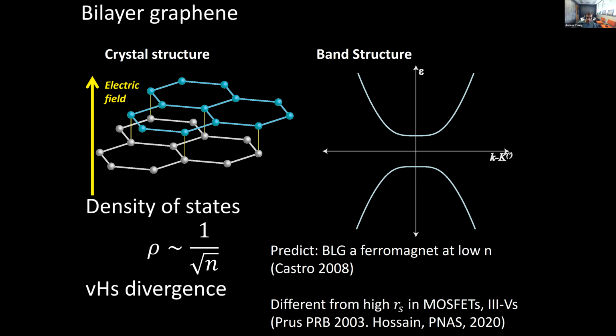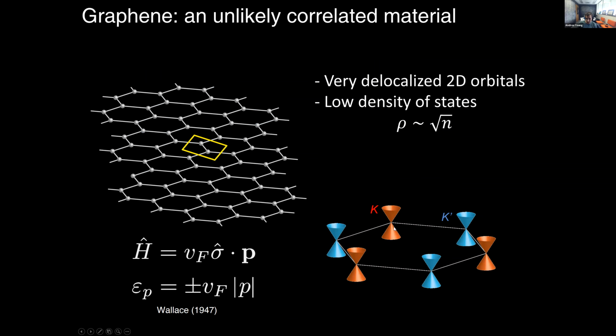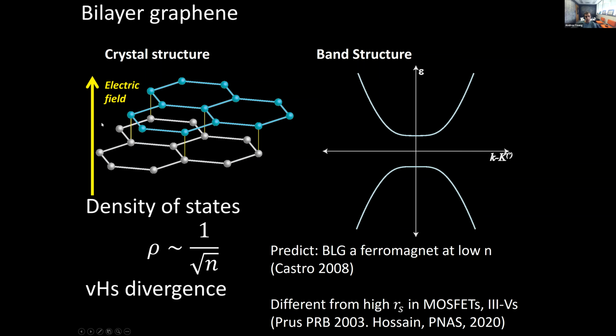Now, most of what I'm going to tell you about, you can basically understand from a very simple addition, which is if you think about the continuum between monolayer graphene and graphite, the most essential thing that happens when you add a second layer is that now electrons can tunnel between these two layers. And that tunneling actually changes the band structure. Here I'm showing a zoom in of the band structure in the vicinity of these K points once you've added a second layer to make Bernal bilayer graphene. It's just two layers of graphite.